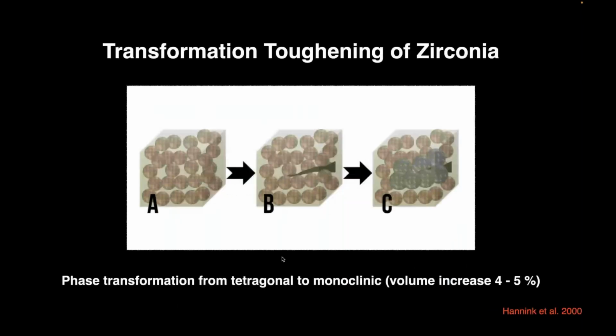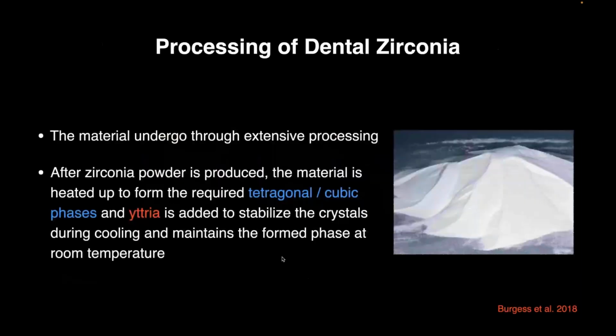So the transformation toughening that we talked about is due to the change from the tetragonal into the monoclinic. When this change happens, the tetragonal crystals will change into the monoclinic, which is 4 to 5% larger in size. So this increase in volume will add compression at that expanding crack. This could happen in a restoration, and it will stop the crack from propagation. And this is known as the transformation toughening of zirconia.